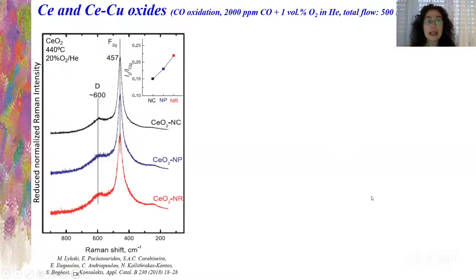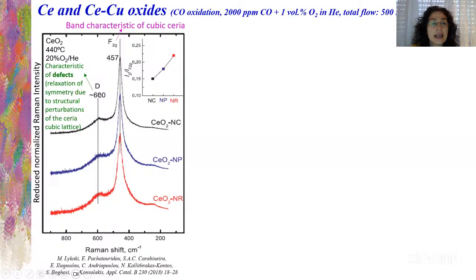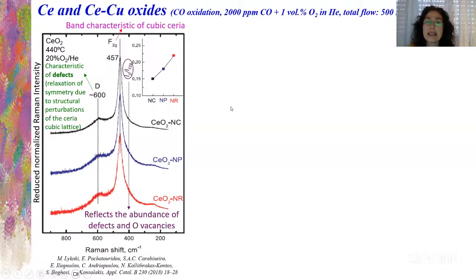Yes, we were here with the copper. Okay, and we also did Raman characterization, and it's interesting because we have these results. This band here, F2G, is characteristic of cubic ceria, which is the structure that we have for ceria. And this band here, the D band, is characteristic of defects, which is the relaxation of symmetry due to structural perturbations of the ceria cubic lattice. So what we have here is the ratio between the intensity of this D band and this F2G band, which reflects the abundance of defects and oxygen vacancies.